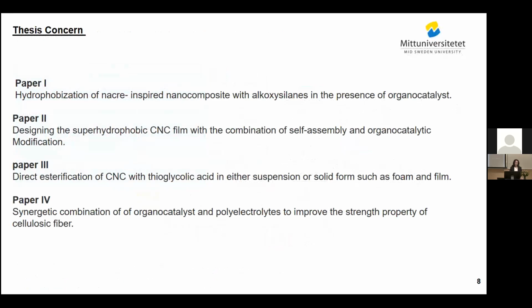Paper 1 is about the hydrophobization of nacre-inspired nanocomposite with alkoxysilane in the presence of organocatalyst. Paper 2 is about preparing superhydrophobic CNC film with the combination of self-assembly and organocatalytic modification. Paper 3 is about the direct esterification of CNC with thioglycolic acid. And in paper 4, we have a synergistic combination of organocatalyst and polyelectrolyte to improve the strength property of fiber.